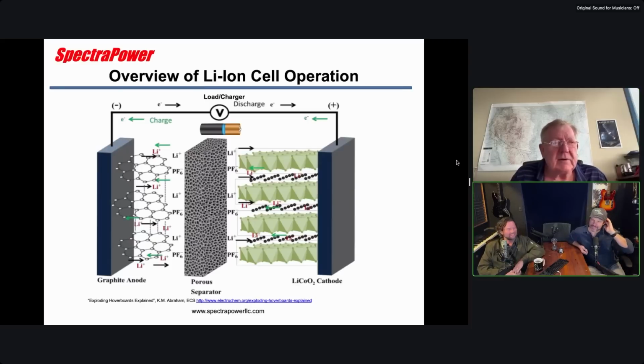Couldn't there be some kind of solution, like including in the charging system some kind of warmer, so you plug the charger in and it warms the battery up and then charges it? Yeah, exactly. In an EV, you'll see modes, I forget the term, but it's basically preconditioning. When you discharge the cell, remember it's like a resistor inside. It's going to self-heat to a certain amount, but what they have to do is get the pack warm enough before they start charging it. Because when you charge it, you'll generate heat just by the resistance in the cell, moving the current through the resistance.